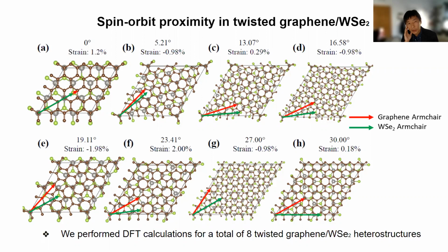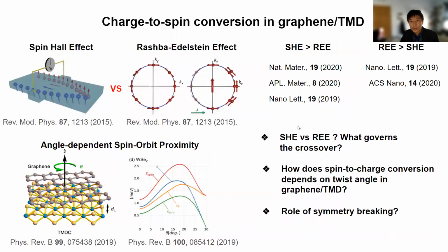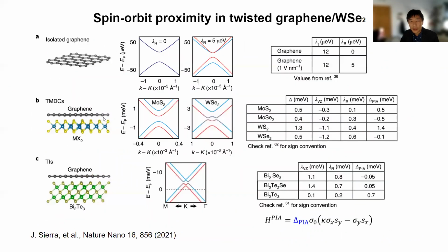If I have to anticipate what might happen, I would guess that this proximity effect is quite weak. If you have a second layer, a bilayer, most of the SOC will be imprinted only on the first layer. I would expect that for the second layer, the proximity effect will be almost negligible. So I'm not too sure if there is any advantage to going to bilayer. Maybe there could be some different symmetry in the bilayer, or the band dispersion is different, and there could be some difference in terms of performance. But at least from the point of view of proximity SOC, the second layer will not be able to benefit much.